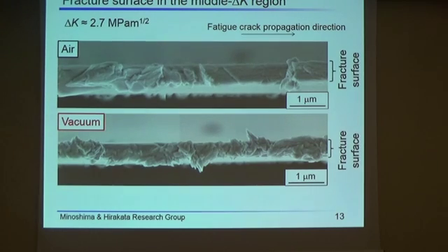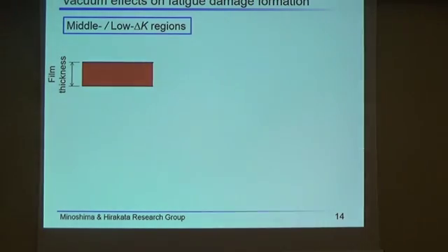So this indicates the presence of vacuum effects on the fatigue damage formation process. Similar fracture surface morphologies are also observed in the low delta K regions. Based on these observations, the vacuum effects on fatigue damage formation were investigated.